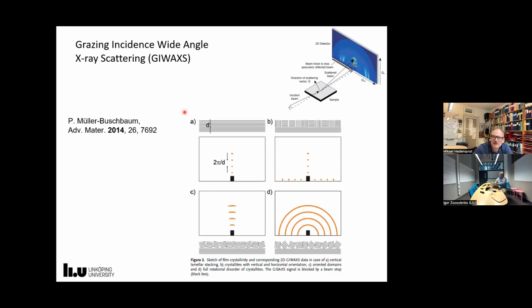So interpretation is relatively simple. So, okay, if you have a periodic structure like this, you are expected to see these peaks corresponding to this Bragg scattering condition, and they correspond to constructive interference. Okay, if you have periodicity in both the vertical direction and horizontal direction, you will have a picture like this. Okay, and in case C, if you have a slightly disordered system, instead of this one, you will have a broadened peak. And finally, if you have a disordered, polycrystalline system, you will have circles like this.